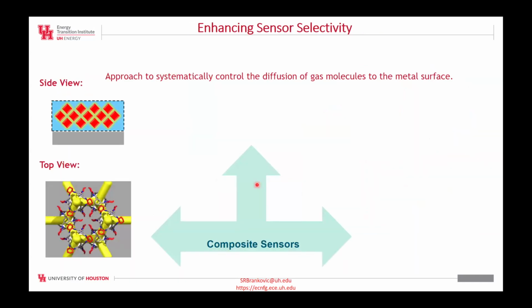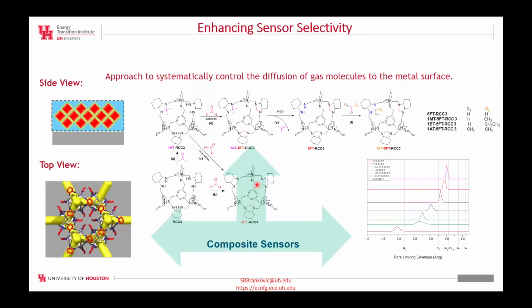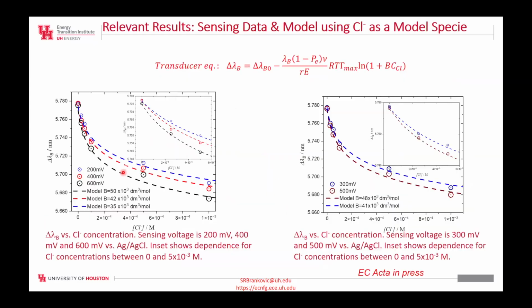And additionally, we can improve the selectivity of the sensor by introducing certain molecular frameworks, in collaboration with Professor Mark Little from Harvard University. We can block the diffusion of any gases other than hydrogen by having a molecular framework with a particular porosity which can only let hydrogen molecules reach our palladium coated surface, but all others will be prevented. Therefore, we can have a super selective sensor, not necessarily a super sensitive one.